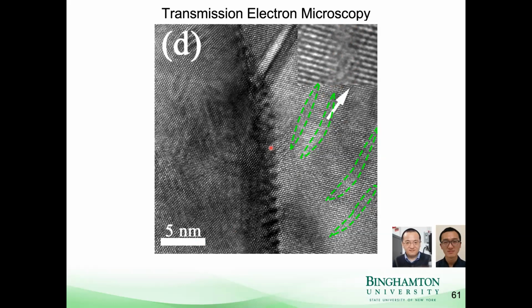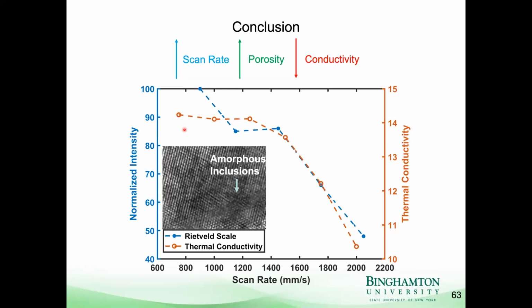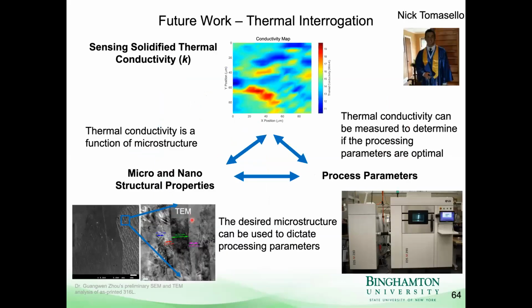So just to summarize here, we found that the thermal conductivity also varied with scan rate, with laser processing conditions, and that this matched the reduction in X-ray diffraction intensity. And we attribute this to some amorphous domains that were created inside the stainless steel. Our plans in this area going forward are to look at how we can use these thermal conductivity properties to print better materials and to also increase the thermal conductivity of selective laser melting parts.